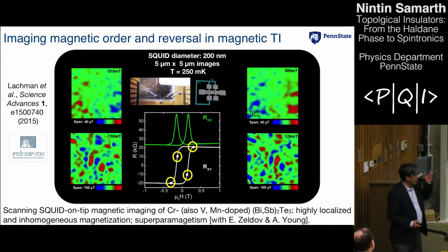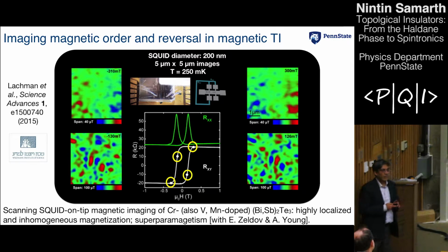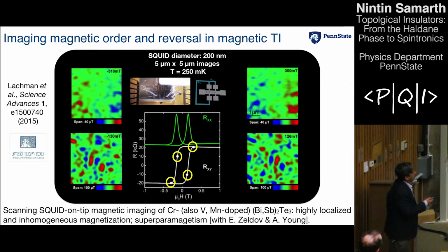And so I approached Eli Zeldov, who's a friend of mine in Israel. He has this terrific technique to image magnetic systems by using a nanoSQUID. So he basically puts a loop of niobium at the tip of an optical fiber. And this loop of niobium has a diameter of something like 200 nanometers. And then he can scan it across a sample, while at the same time, they can measure the transport. So here is this anomalous Hall effect, not quite quantized because we're at 250 millikelvin, we're at too high a temperature, but it's reaching there. And then here is the longitudinal resistance.